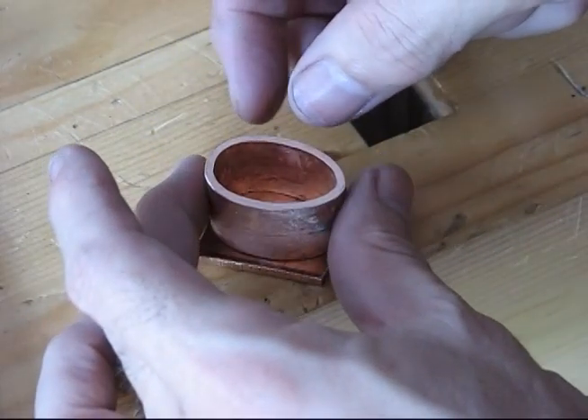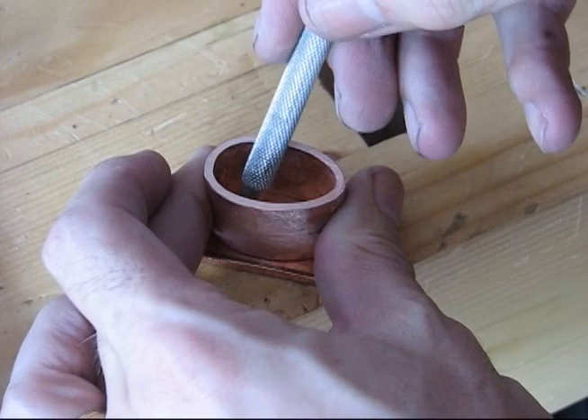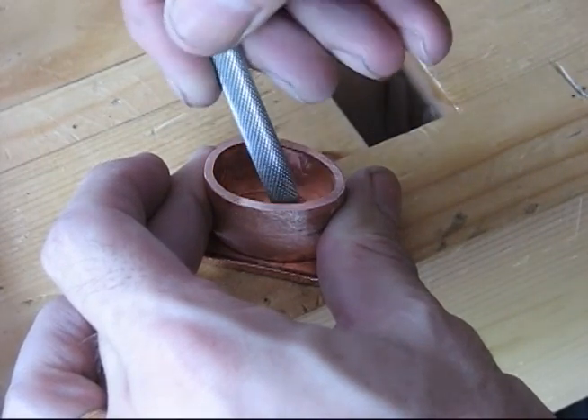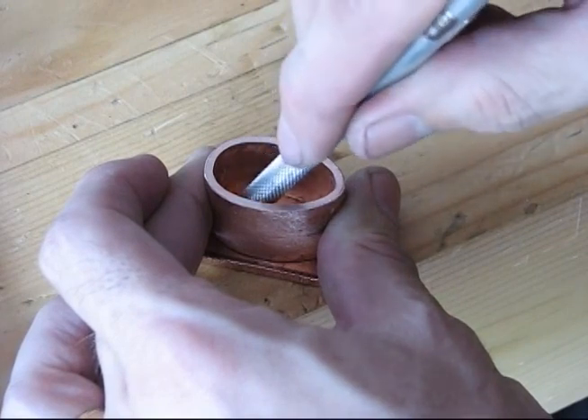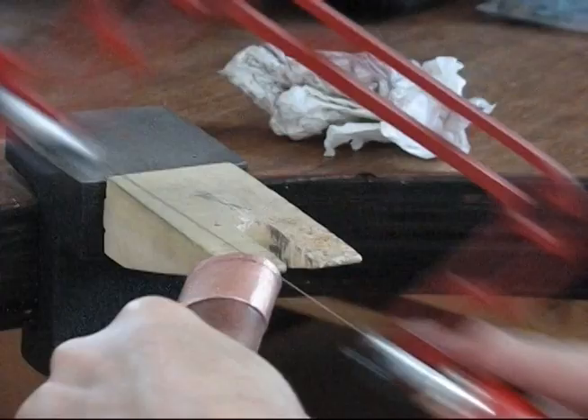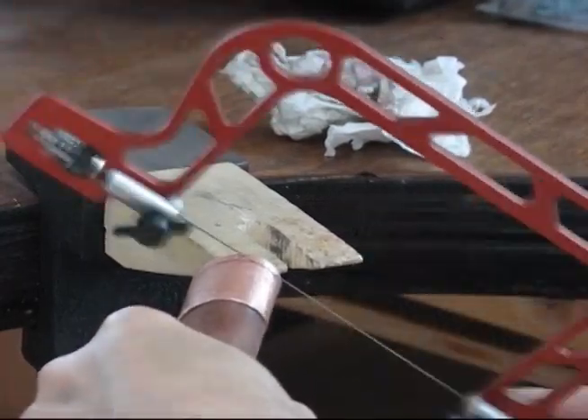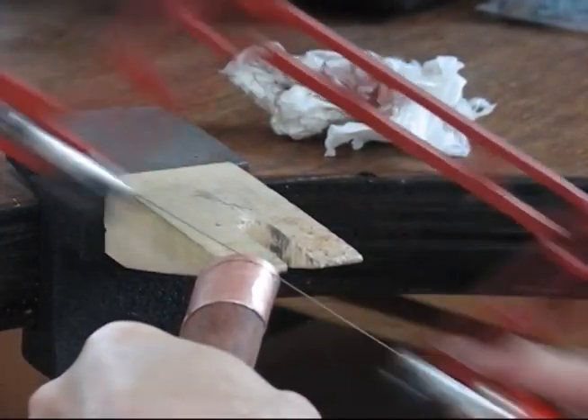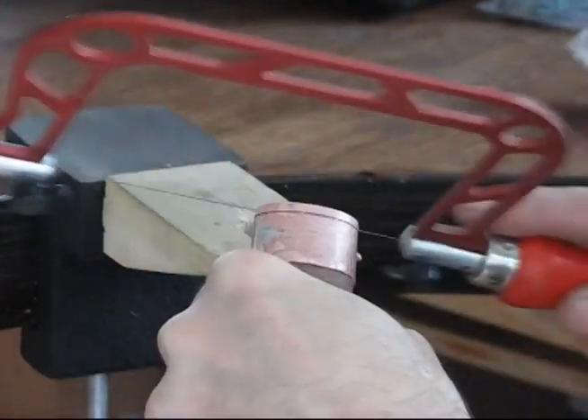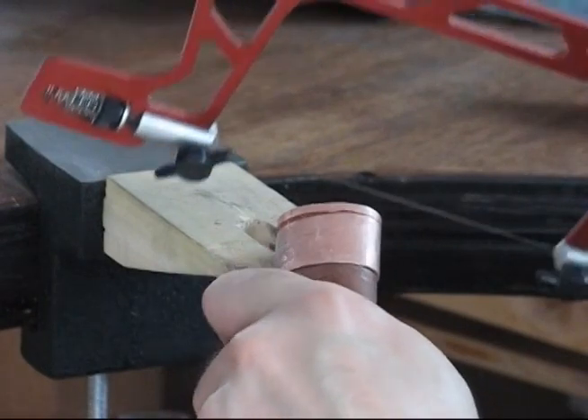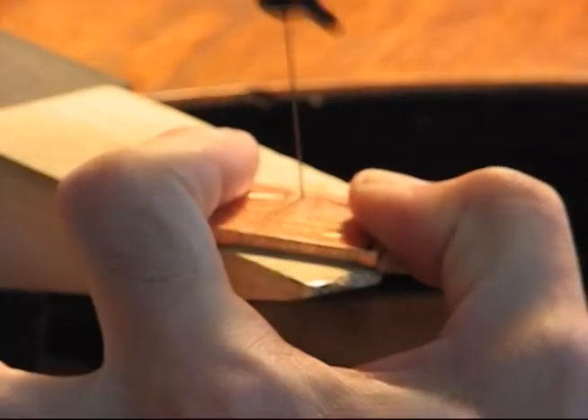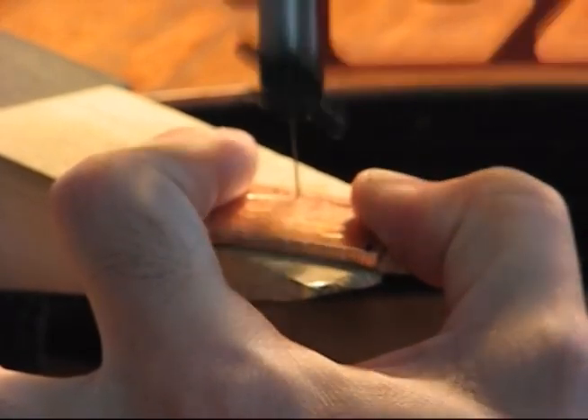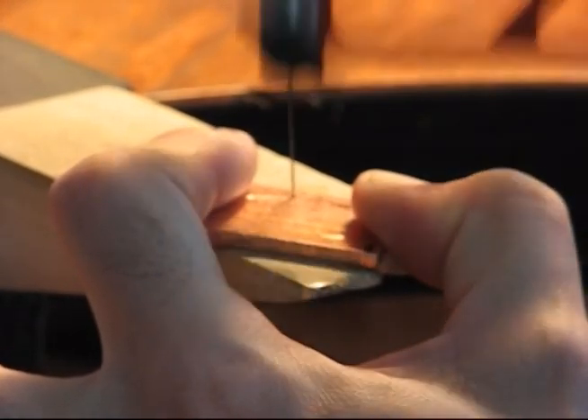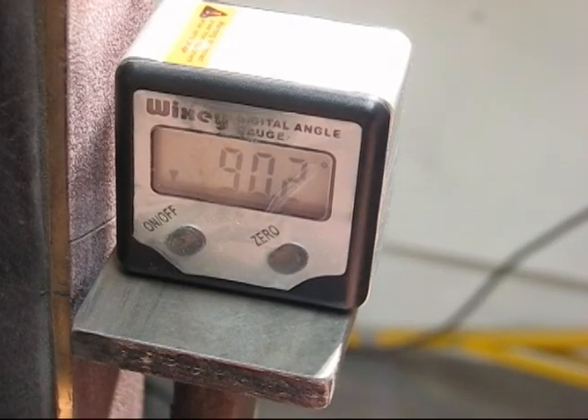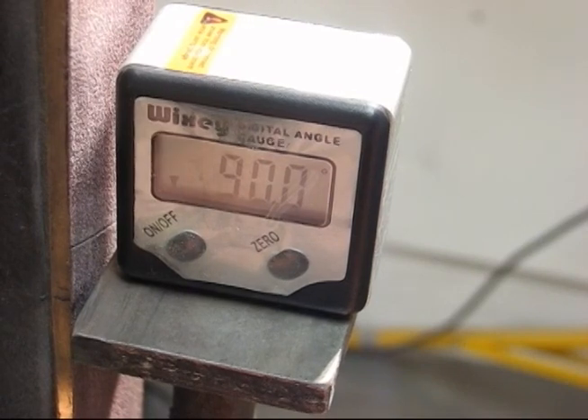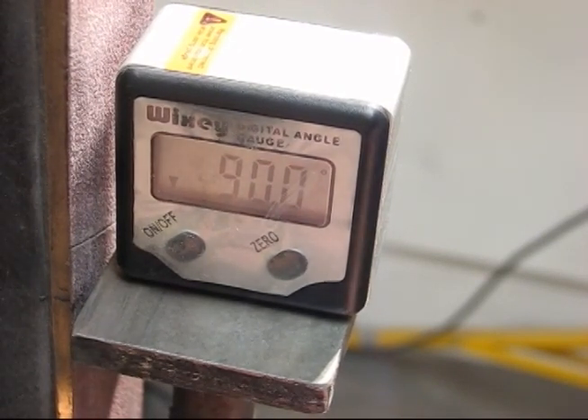The profile for the cap is inscribed on the copper plate using the band as a template. Excess material from the band is removed with the saw. Then the copper plate is cut, following the inscribed profile. The resting support on the belt grinder is adjusted to be 1 degree off from being perpendicular. This creates a taper in the plate that will allow it to be pressure fitted to the band.